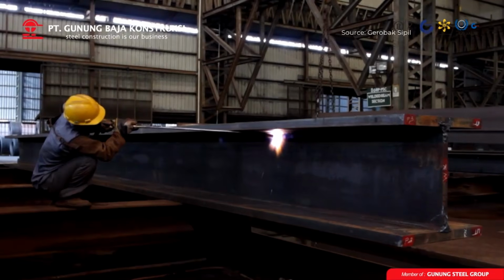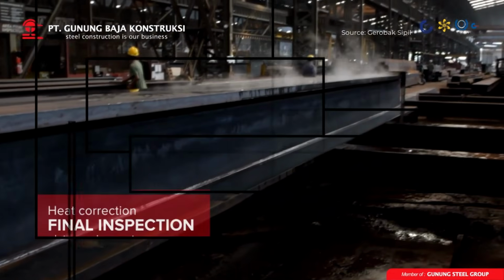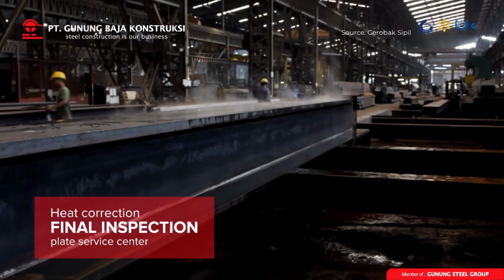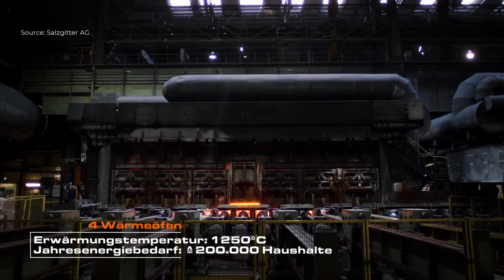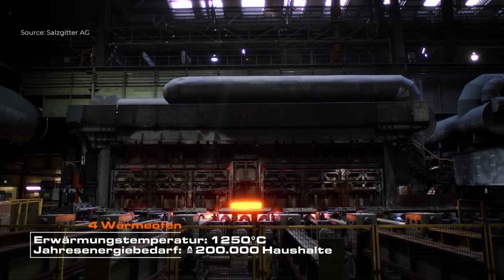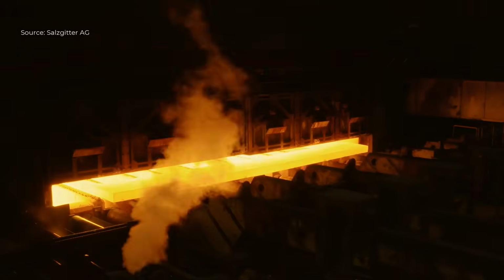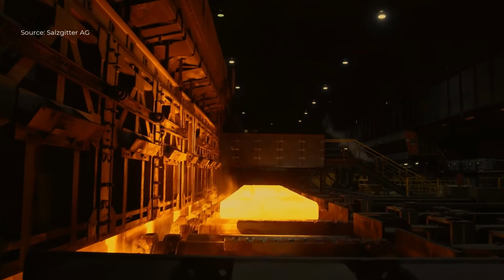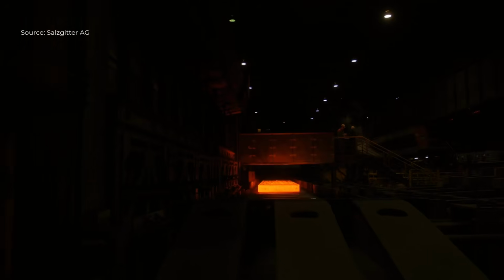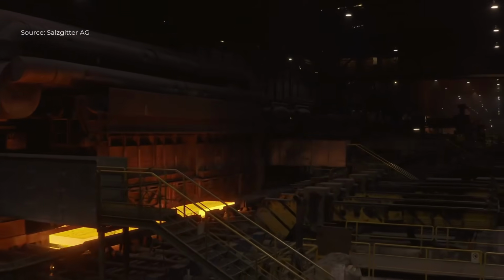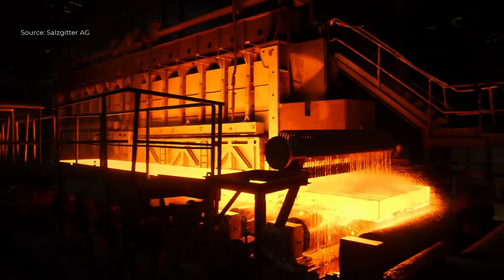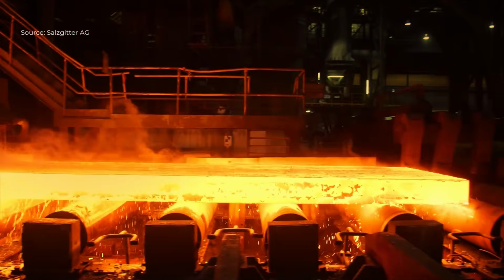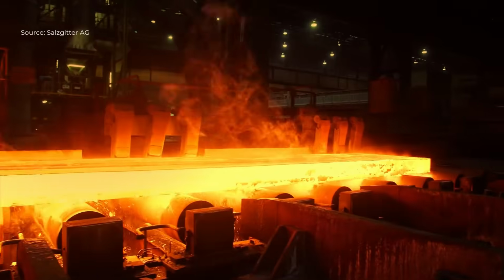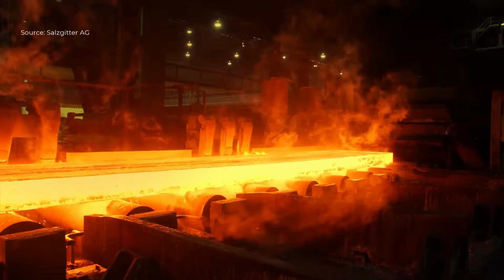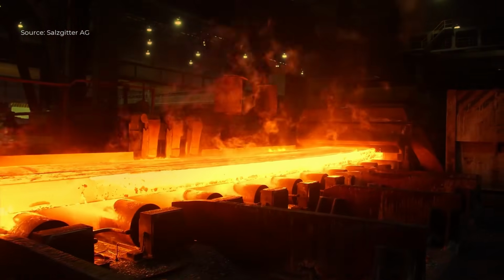Through these controlled and sequential steps, a welded beam is produced with the required strength, accuracy, and reliability for structural applications. The process begins with thick steel slabs being charged into 4 reheating furnaces, where they are uniformly heated to approximately 1250 degrees Celsius. This step ensures the steel reaches the plastic state required for intensive deformation. The furnaces operate continuously and supply hot slabs to the rolling line, consuming energy equivalent to that used annually by around 200,000 households.